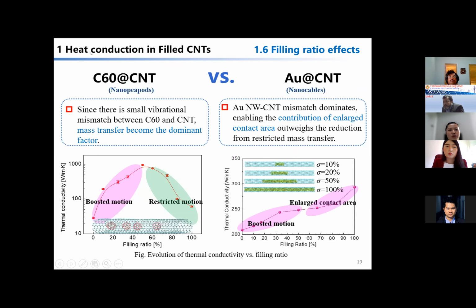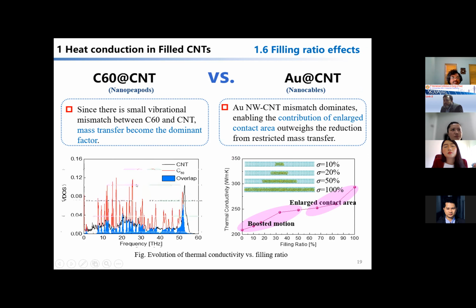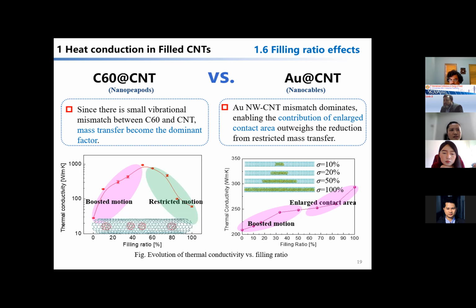Let's compare the nano-peapod with nanocables. For the nano-peapod, since there is small vibrational mismatch between carbon-60 and the tube, we can have energy transfer, the blue shadow in this picture. Since there is a small vibrational mismatch between them, mass transfer becomes the dominant factor. That is, with increased filling ratio, the thermal conductivity increases first with boosted motion of carbon-60 and then decreases with restricted motion of carbon-60. It's a non-monotonic dependence on the filling ratio.